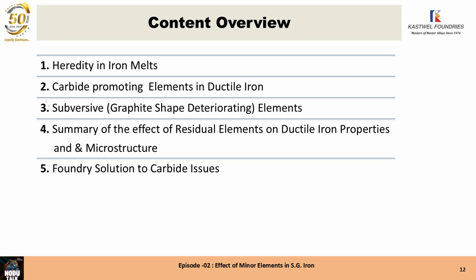Last time we spoke about the five basic elements in ductile iron: carbon, silicon, manganese, sulfur, and phosphorus. We saw that to produce ductile iron, we have a very small window in which to make good quality ductile iron. On the left hand side, we have the limitation that the carbon plus 1/7 of the silicon should be more than 3.9%. That was seen last time.